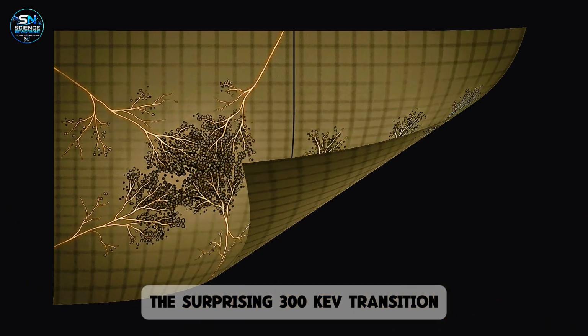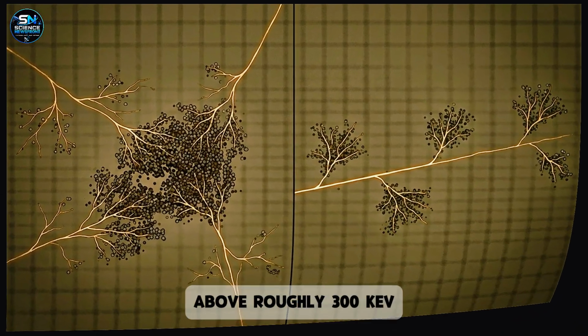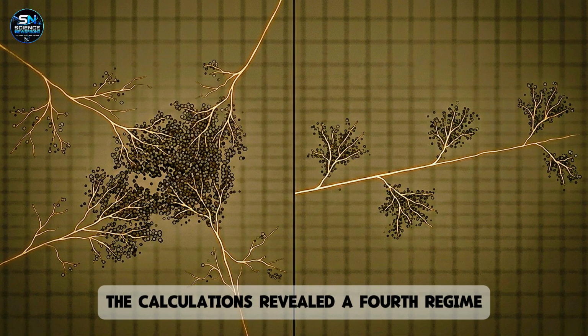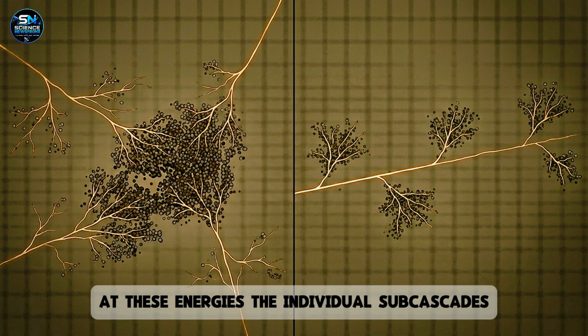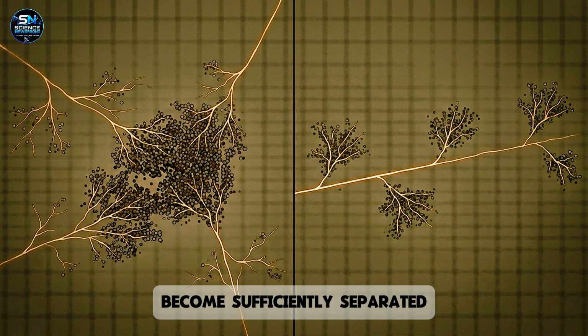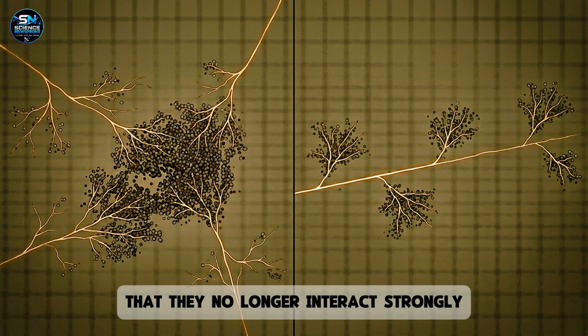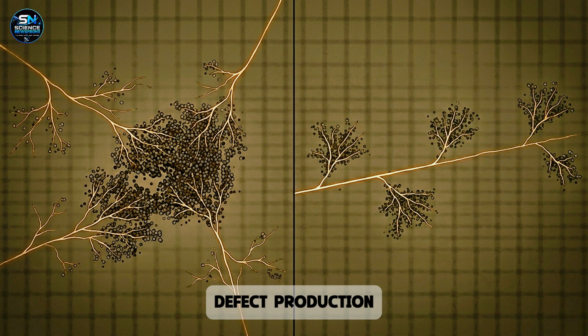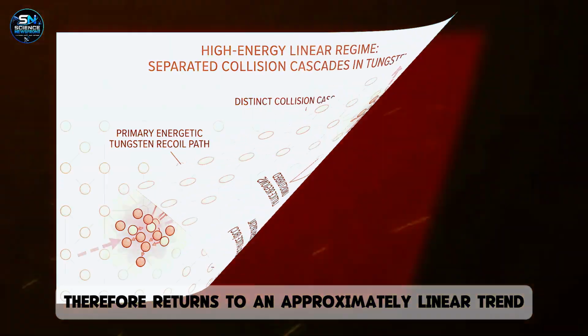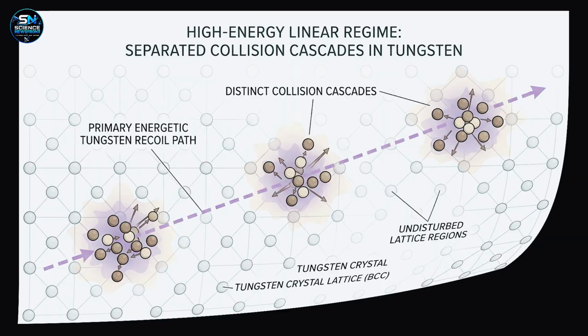The surprising 300 keV transition. Above roughly 300 keV, the calculations revealed a fourth regime. At these energies, the individual subcascades become sufficiently separated that they no longer interact strongly. Defect production therefore returns to an approximately linear trend.